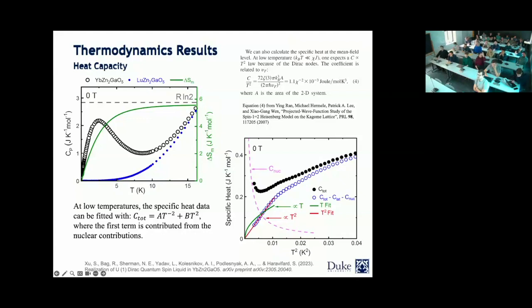So this is for the ytterbium compound. And also we made the lutetium compound, which is isostructural to the ytterbium one, but it's non-magnetic, so that we would be able to subtract the phononic contributions and then look at the magnetic entropy. The magnetic entropy goes to R log 2, which is indicating again what we have seen before, that you're dealing with a ytterbium 3+ effective spin 1/2.